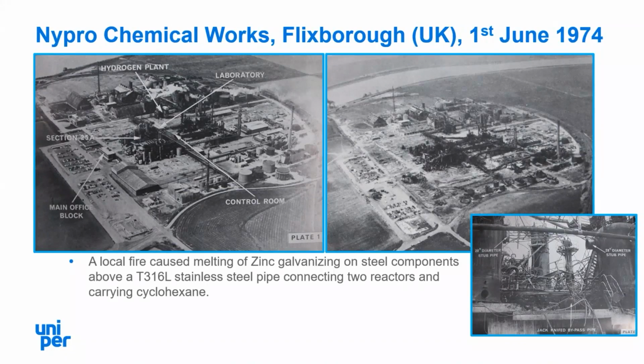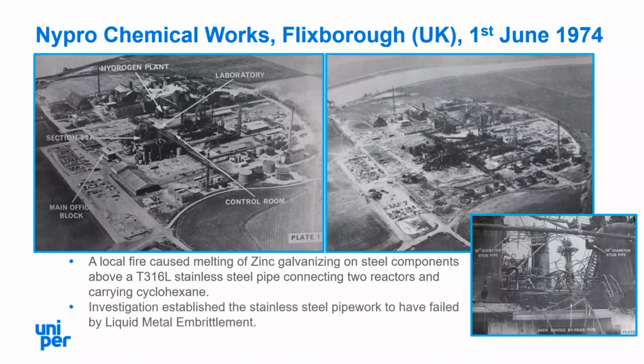Investigators subsequently identified that a local fire caused melting of zinc galvanizing on steel components above a 316 stainless steel pipe. This piping connected two reactors and was carrying cyclohexane. What they established was that the stainless steel pipework had failed by liquid metal embrittlement associated with the zinc dripping down onto it, leading to the catastrophic failure which you can see. The incident itself killed 28 people, injured another 36 from a total weekend workforce of 72. Gives a measure for the scale of devastation which was seen there.